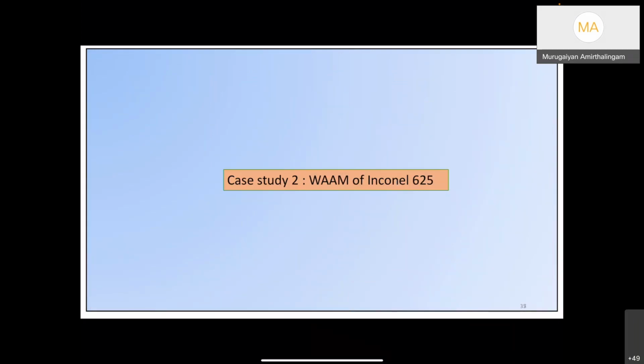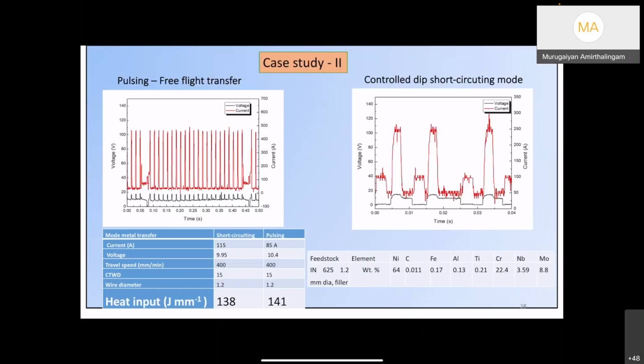Not a problem. Good. In another application, we have to get a microstructure exactly opposite to what we have seen in the copper. Superalloys, Inconel, for example Inconel 625, are widely used in high temperature and high corrosion applications, isn't it? So in these alloys, we need to get a directionally solidified microstructure, opposite to what we achieved.